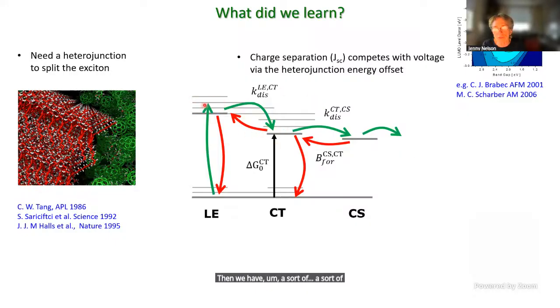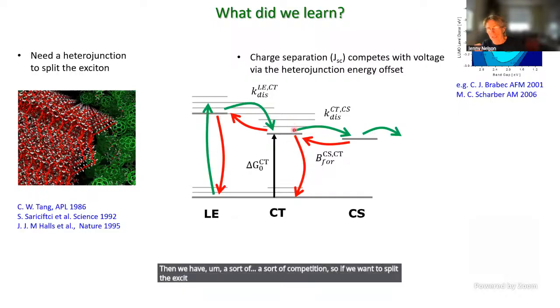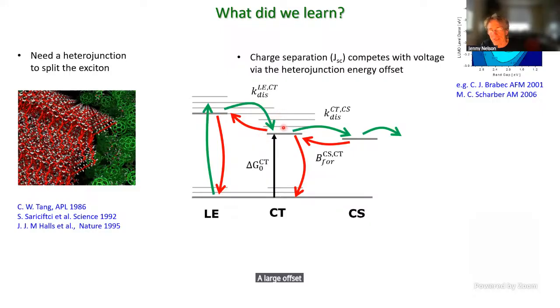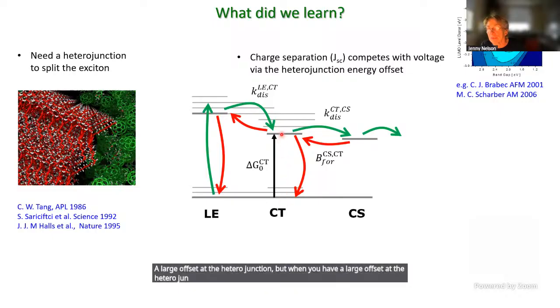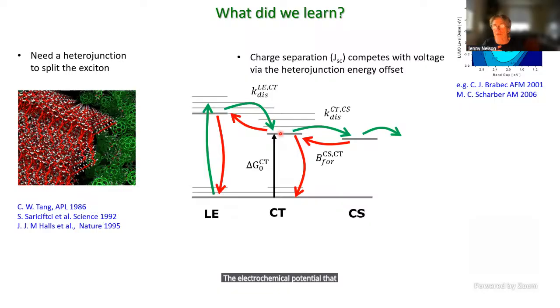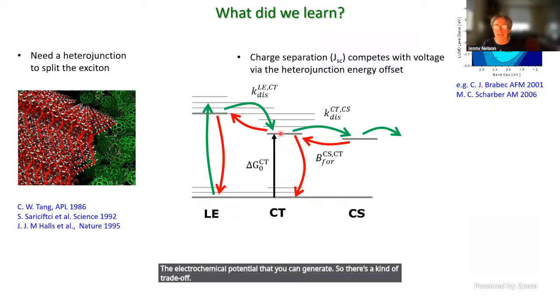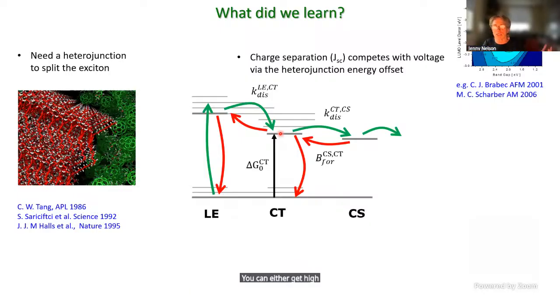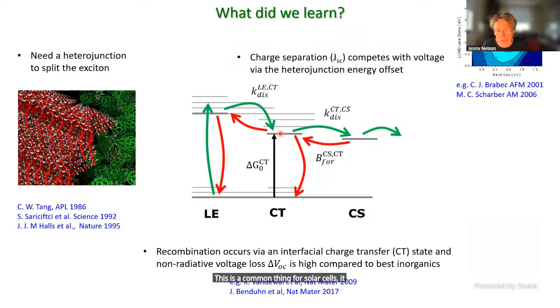If we want to split the exciton and collect charges very efficiently, that will require a large offset at this heterojunction. But when you have a large offset at the heterojunction, that limits the voltage, the electrochemical potential that you can generate. So there's a kind of trade-off. You can either get high current or high voltage, but you don't usually get them both together. This is a common thing for solar cells. It also applies for ours.